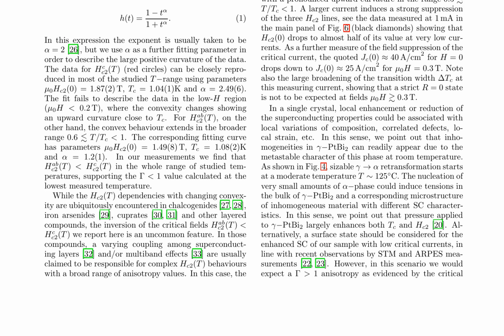This contrasts with other layered compounds, where complex Hc2(T) behaviors are typically explained by varying coupling among superconducting layers or multiband effects. The study suggests that inhomogeneities in the sample may influence the superconducting state, despite the high-quality sample. The asymmetrical transition width in ρ(T) at fixed H provides evidence for the presence of such inhomogeneities. This finding has implications for understanding the role of inhomogeneities in shaping the superconducting properties of γ-PtBi2.